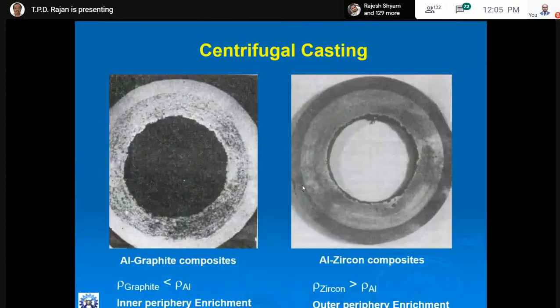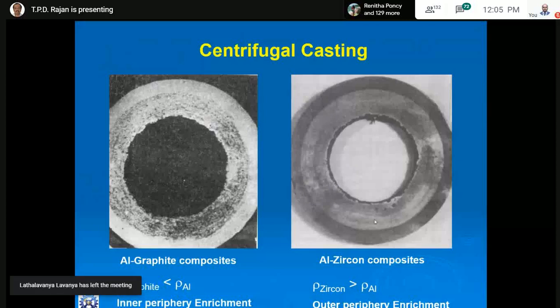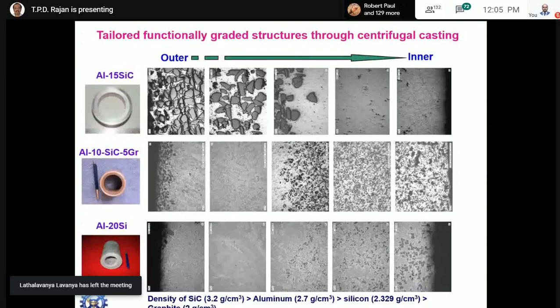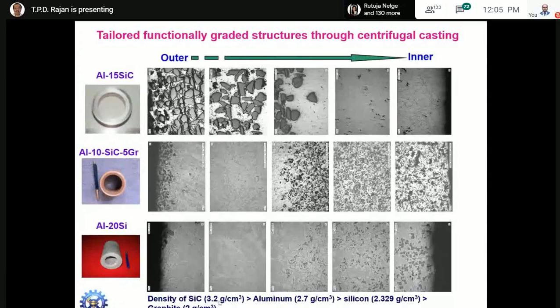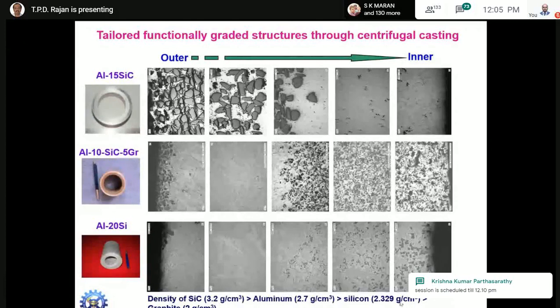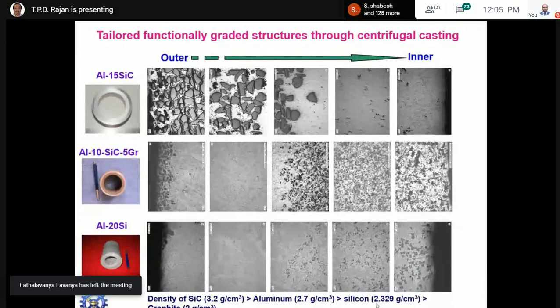So once you centrifugally cast it, because of the variation in density, if the density is lesser than the reinforcement, it goes towards the interior periphery, and if the density is higher, then it goes to the outer periphery. So in aluminum graphite composite, graphite density is lower, so it goes to the interior periphery, and zircon, whose density is higher, goes to the outer periphery. So you can have a functionally graded composite. In the case of the aluminum SiC system, the SiC particles segregate towards the outer periphery because of the higher density of SiC, 3.2 gram per cc, than that of aluminum, which is 2.7. However, graphite is 2 gram per cc and silicon, not silicon carbide, silicon, the density is 2.3, so it gets segregated towards the interior periphery.